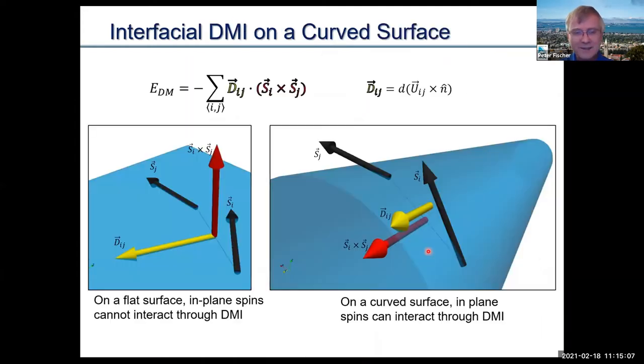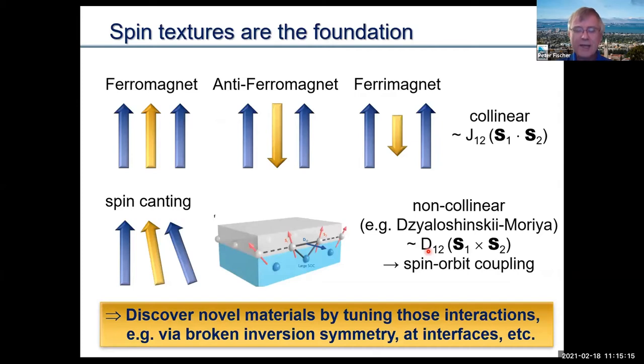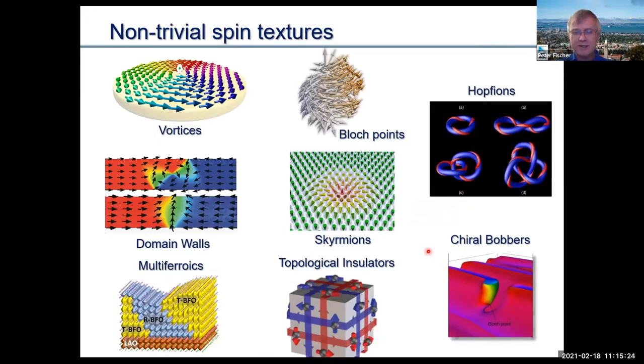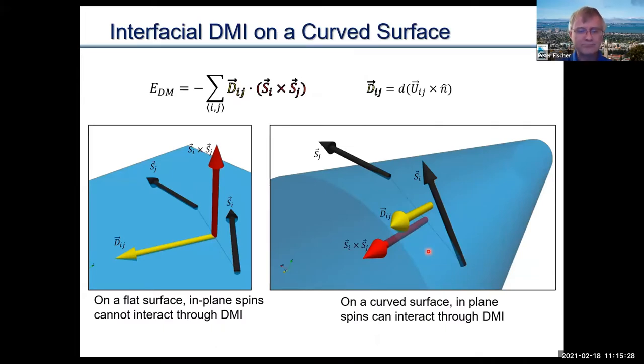Now, let me share with you one other thought. So this is a very fundamental consideration of how neighboring spins couple and how they basically align. Well, that is true for planar systems. But if you put them, let's say, in a curved geometry on a curved surface, and this could happen by design, let's say, on the surface of a nanowire or on a sphere, things like that, well, what it means is that all of a sudden, an exchange interaction, which you might think is parallel, turns out to be no longer really just parallel, because if you put two spins on a curved surface, those that are just coupling by exchange, well, they do have an angle, and all of a sudden, they also have an interfacial DMI on this curved surface. So what I'm saying is, by adding to a planar surface the radius, the curvature, you end up with a completely new degree of freedom that you can play with, and this is what is really exciting.